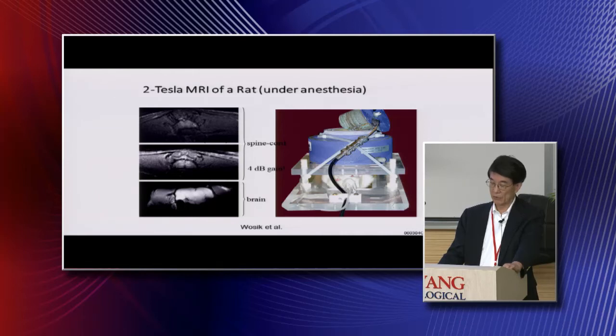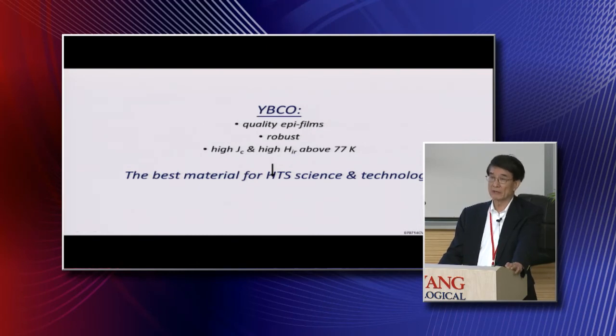And this is just to show you one of the impressive things in magnetic imaging. For example, when you try to image the spinal cord injury of a rat, you have to implant the copper coil sensor underneath the skin of the poor mice, and therefore when you take the imaging, it's not very good, as indicated here, with the copper. But when you use superconducting material, you only have to cool it from the top, the sensor is inside this styrofoam cup, and then you can see the quality of the image is tremendously improved, even detecting the brain and all that.